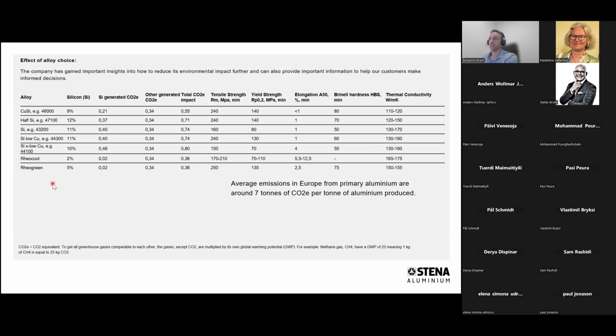This table also shows kind of the similar setup. So we have the different alloy groups here, going from the high copper containing alloy groups, 46,000 for instance, as I mentioned, and then going downwards to lower copper contents. And then we have added then the silicon content, and also we have looked at how much silicon are we adding on average to these alloying groups. And we have looked at how big are the emissions from the actual silicon additions. So here you see the silicon generated CO2 emissions, and as I said, it's lower for this 46,000 alloy with a bit higher copper content, and then it goes down into higher silicon additions and higher generated CO2 equivalents then.